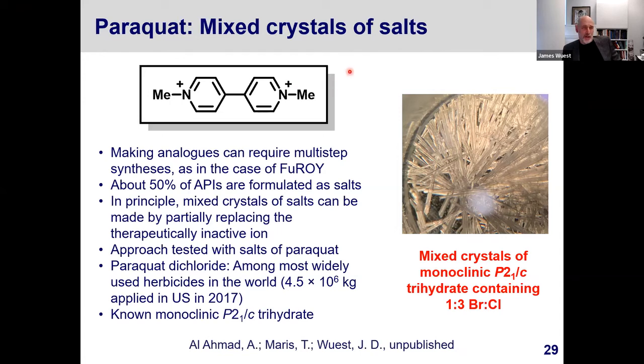We began to look at salts of paraquat, the dimethyl viologen compound, the dication that's shown here. In the work we did with furoy, we had to invest a lot of time in making furoy itself. It was not a trivial synthesis. And so you may think, well, using these analogs as heteroseeds or forming mixed crystals, that's a lot of work. But in fact, about half of active pharmaceutical ingredients are formulated as salts. So there's the possibility that instead of actually making an entirely new compound, you can just replace the biologically inactive ion and start making mixed crystals and exploring the use of these mixed crystals in that way.